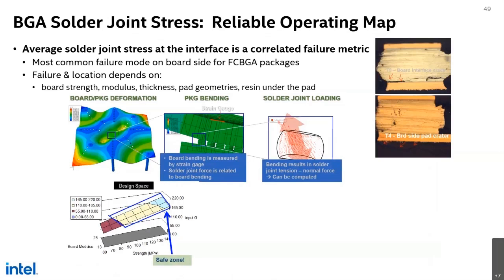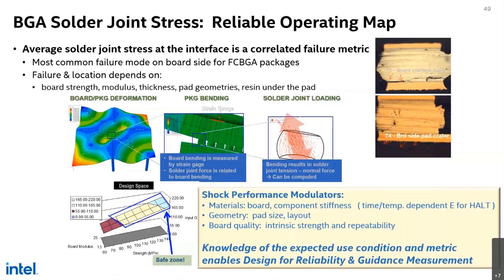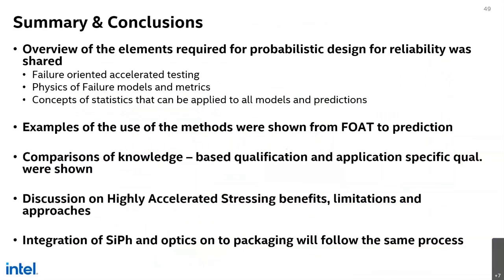You can find a safe zone essentially for a current dynamically applied stress. So this really turned from a HALT type of a test where you were looking just to break something into something where if you do the work, you can dig in and you can find out how you can apply it to different geometries and elucidate how you can do better designs. So summary is that we have all of the requirements or elements for a probabilistic design that we've shown. We gave some examples of the failure-oriented accelerated testing, and we compared the ways to do qualification, knowledge-based versus stress-based, and then lastly, what can we do with the highly accelerated stress testing?